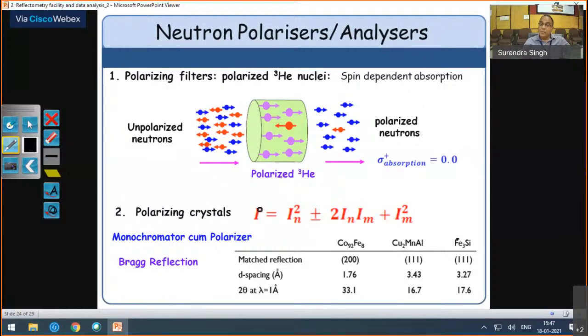That's why we have, after reflection from this 111 plane of copper 2 MnAl material, polarized neutron. Okay, and there are a few other materials I have listed over here, and a particular plane which satisfies this condition and gives you the polarized neutron due to the Bragg condition.